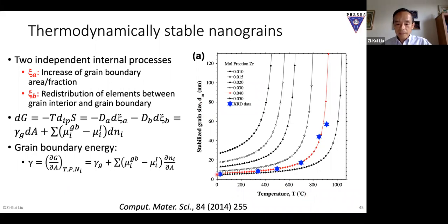The blue symbols here are the experimental data from X-ray at different temperatures, for different zirconium concentrations. The red one is 0.04, that's the experimental composition. With that composition, we did the calculation and predicted thermodynamically stable nanograin of the iron-zirconium binary system.